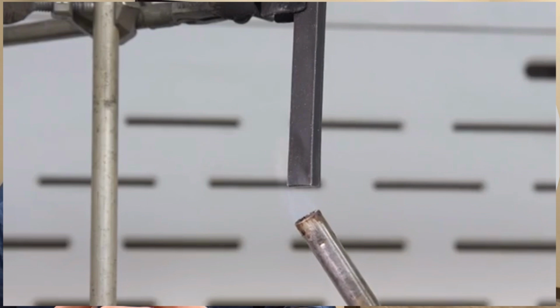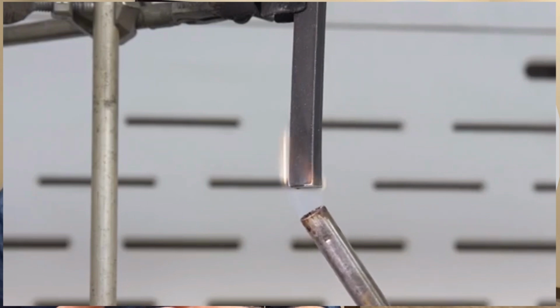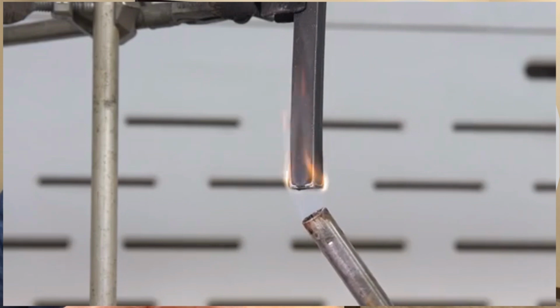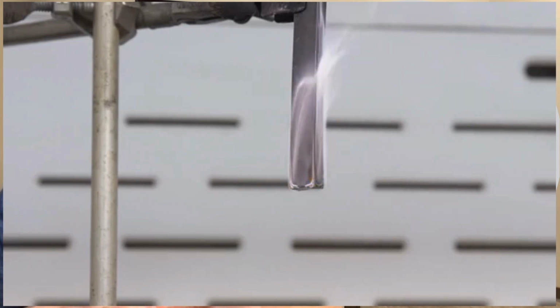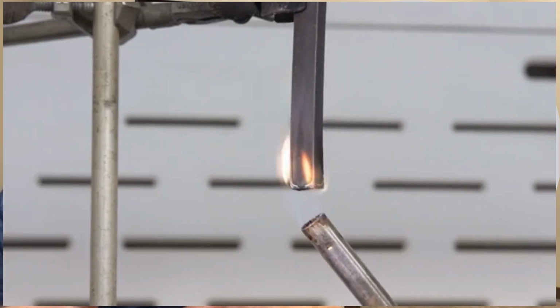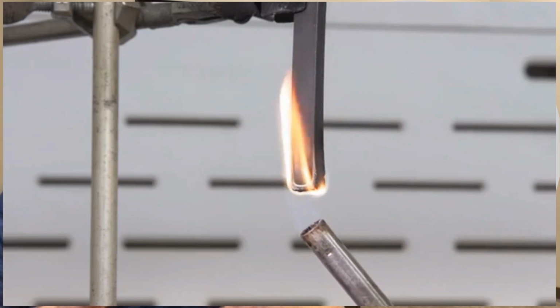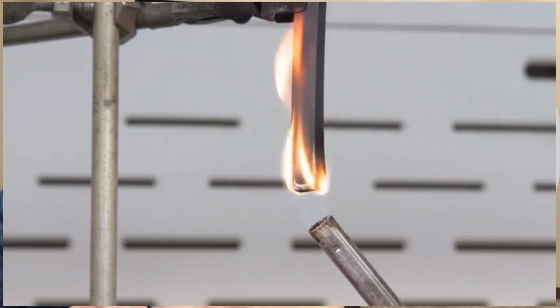We set a Bunsen burner to the specified flame intensity. We then set incident of the flame to the sample at 10 millimeters and burn the sample 2 sequential times for 10 seconds each. The total self-extinguish time for each burn must be below 10 seconds for the sample to pass at that thickness.